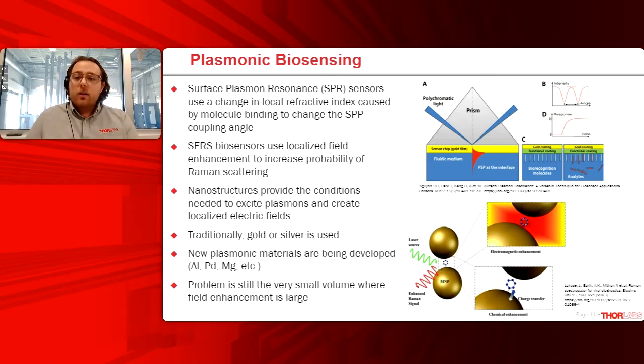And at that angle where that reflection drops, you are actually absorbing that light, and you are coupling that light to surface plasmon polaritons along the surface of that gold film. Now, if you were to bind some molecules that you're interested in sensing to the gold surface, you're now changing the localized refractive index, and therefore the angle that your surface plasmon polariton couples will change. And you can use this type of scheme to perform some biosensing.